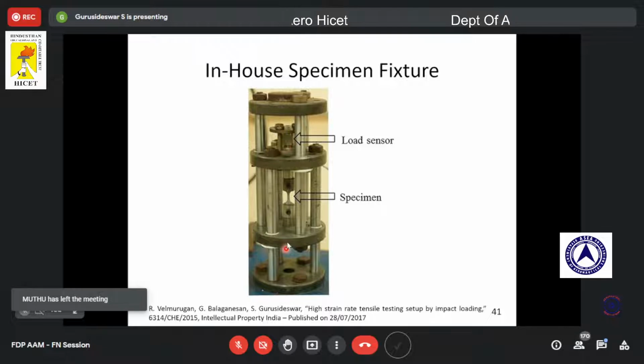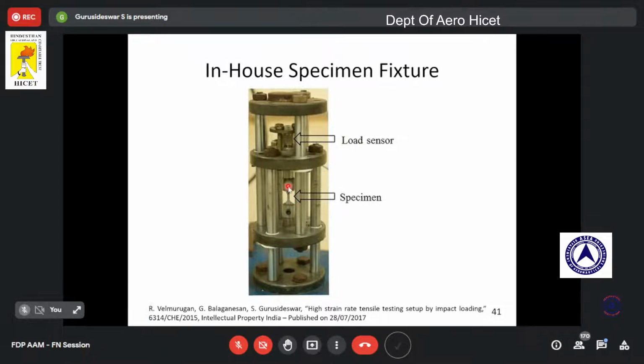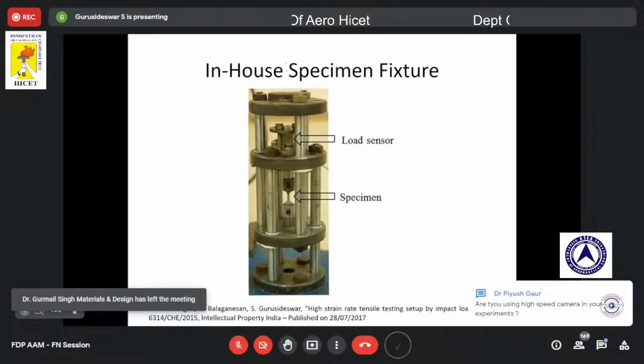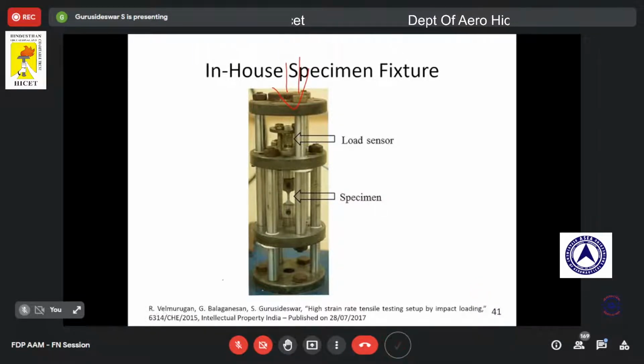Here you can see it has a mobile jaw. The sample has been fixed here. Maybe I can show using a pen: when the drop mass hits this fixture, the sample will experience tensile load, and it will lead to failure. The tensile load can be extracted from the load sensor, which has been mounted at this point. So this is the principle. From this idea, we achieved a high strain rate, and we also designed a fixture to load the sample at high strain rate, and we use a load sensor to record the load data. This figure shows the specimen fixture, and how the sample has been mounted in this drop mass setup.